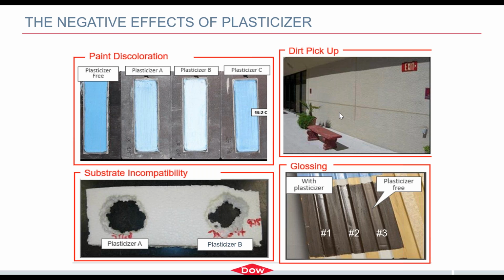Also, dirt pickup resistance. So this is a commercial building where the seams in the building here were filled with a sealant and then top coated with an elastomeric wall coating to get a uniform visual of the wall of the building. So what again happens over time as the plasticizer migrates to the surface, it can also create a sticky surface on the sealant. And once you have a sticky surface, depending on what the environment is like, will depend on how much dirt gets picked up on the surface. And then all of a sudden, you're going from an aesthetically pleasing, uniform looking wall to a wall that has these dark seams in it.